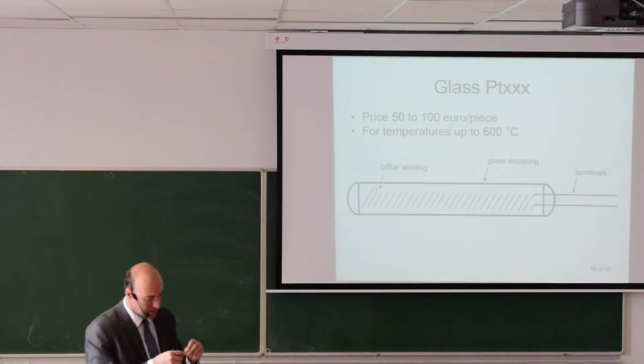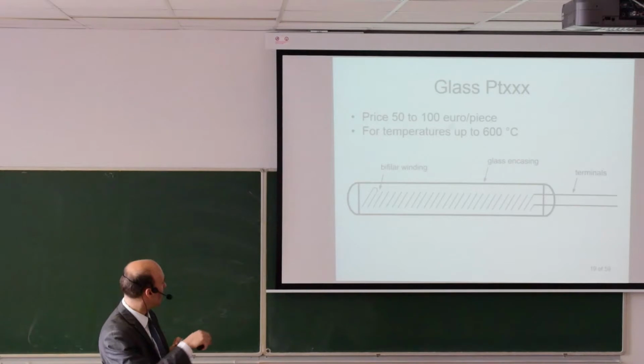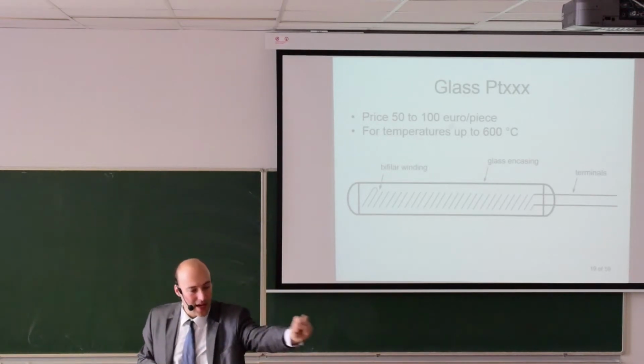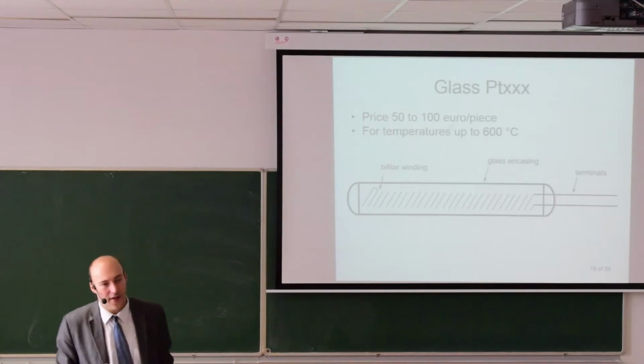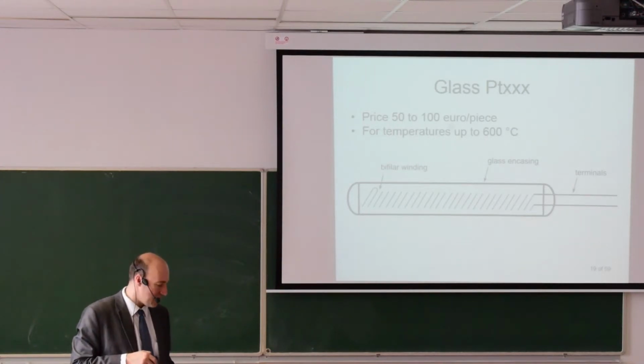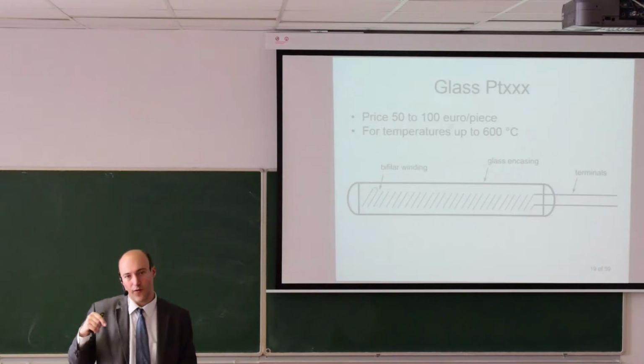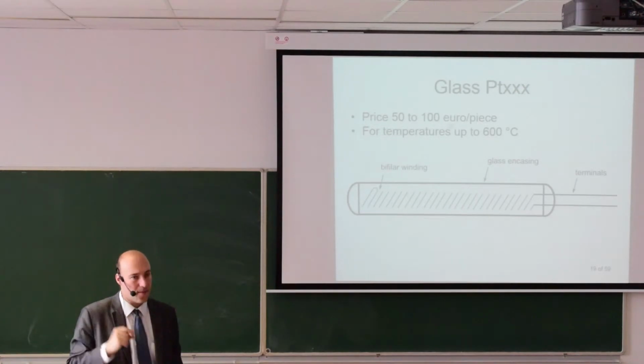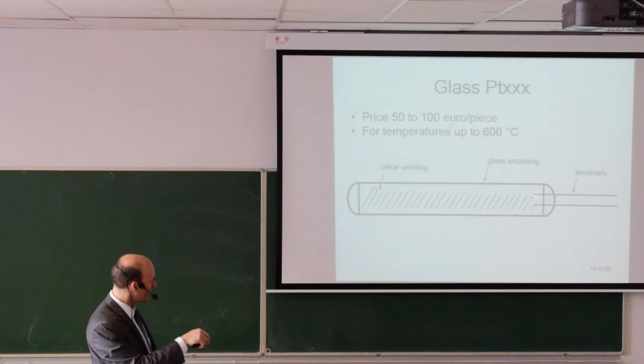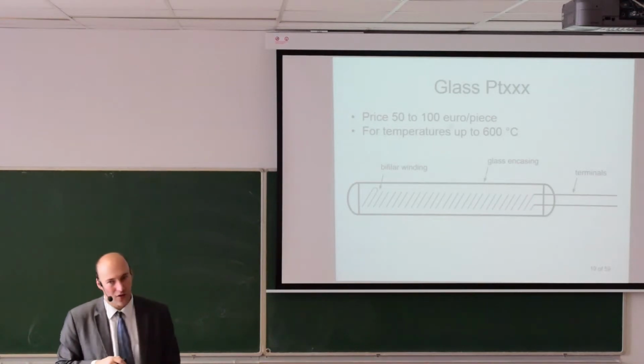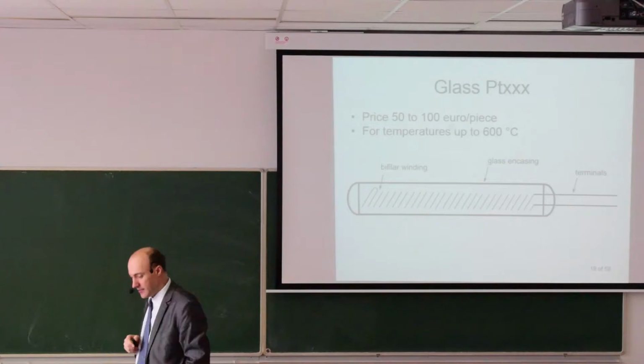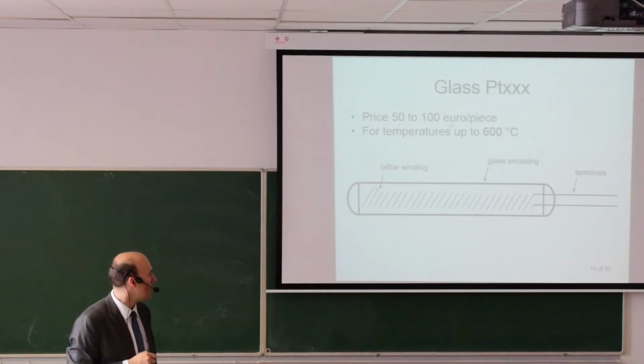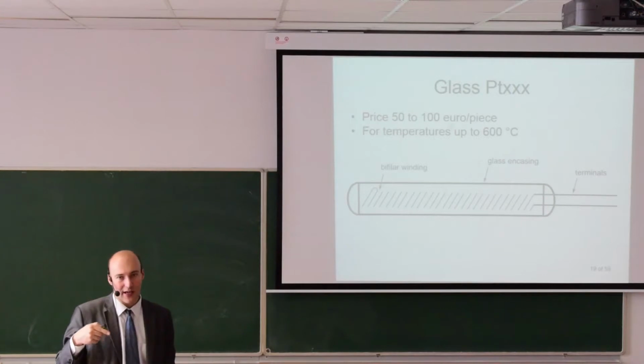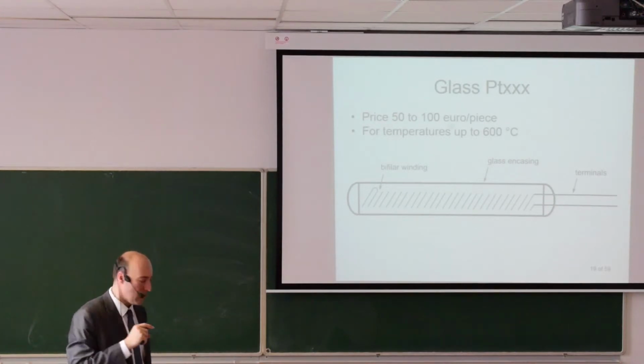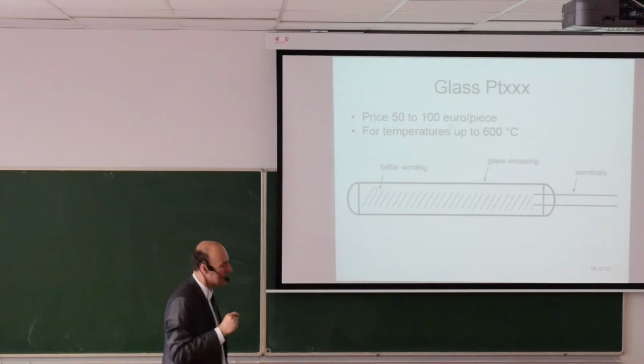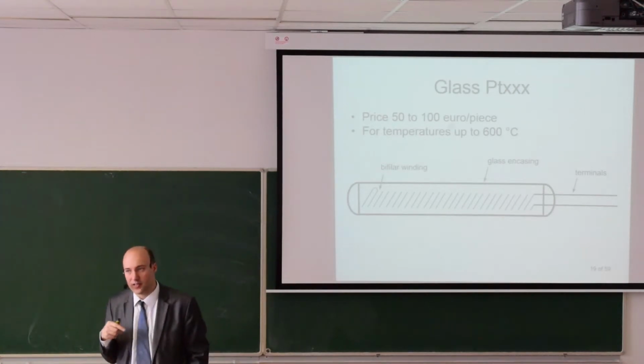It's here. So it's a small cylinder from glass. Looks like this. And inside the cylinder, you have a very thin platinum wire. The typical diameter of the wire is like 0.05 millimeters. So it's a very thin wire. It's wound in a special way that's called bifilar winding. And this kind of winding will limit the inductivity of the sensor itself. So we are looking for changes of electrical resistance, and we don't want any additional inductivity in the sensor.